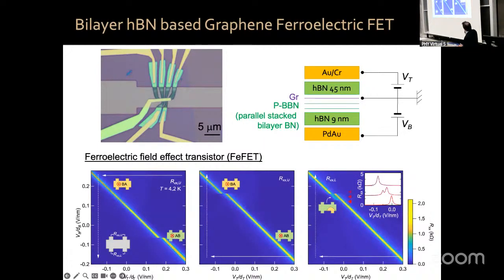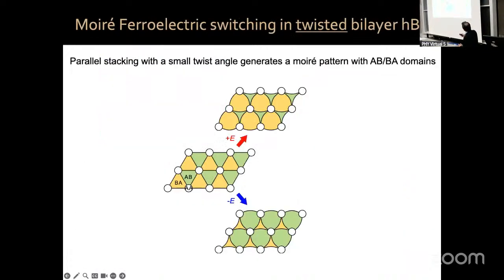If you do this in a map, this is a dual gate. Now we have 2 gates, so that we can apply a transverse electric field. You can see how this switches abruptly, and then if you reverse the gate voltages, you switch back at a different electric field, so there is a hysteresis, a coercive field. Occasionally, you can catch a domain wall in between your contacts, so you see both peaks for both the AB and BA domains. This is something that happens for 0 degrees.